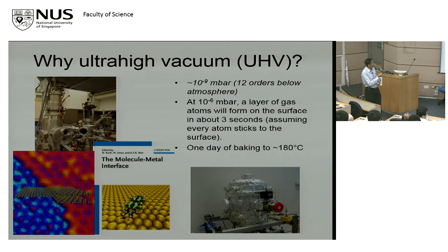And now typically we can get to 10 to the minus 10, 10 to the minus 11 base pressures. And that's important because we want surfaces that are clean. So this STM image shows a surface, at least within this length scale, you can't see any other contamination on it. And then you can study single molecules on the surface and so on. So that's basically why surface scientists are so bothered.